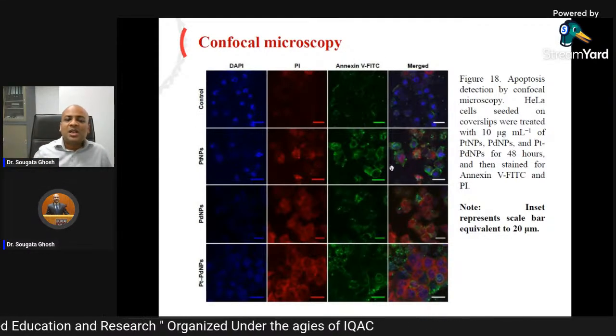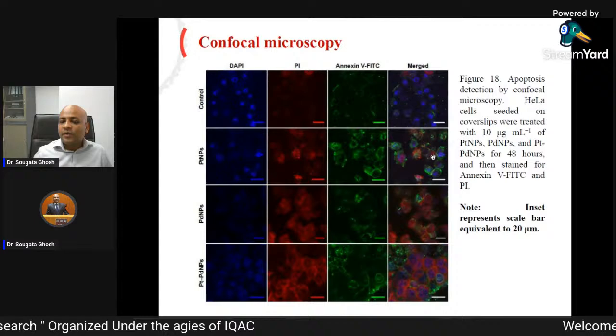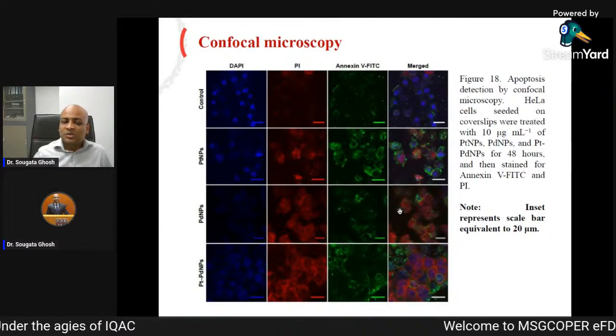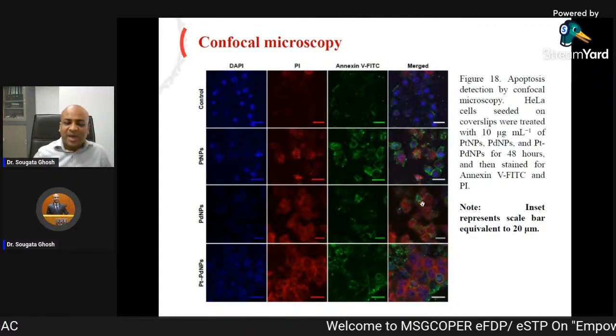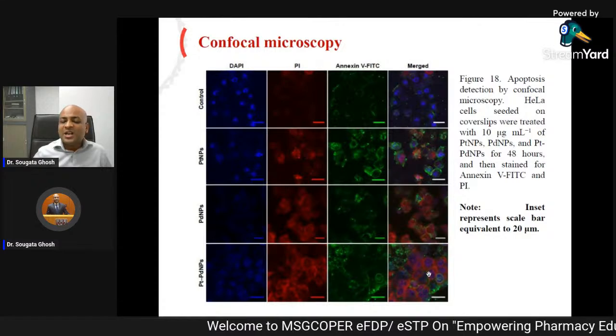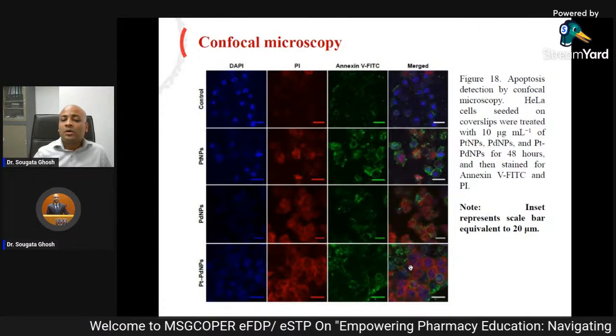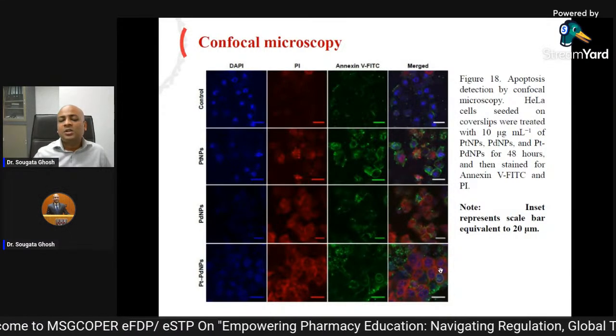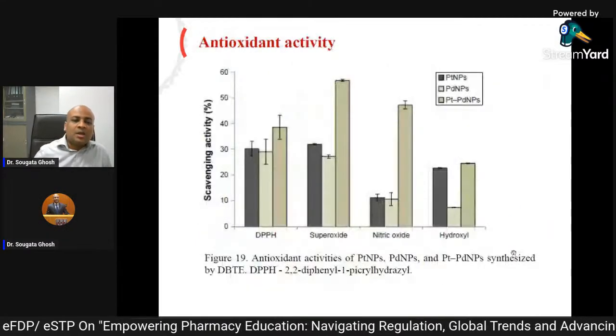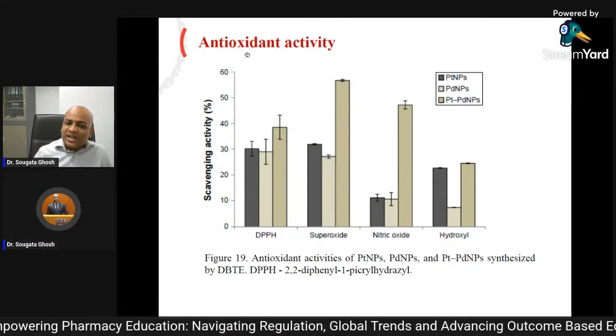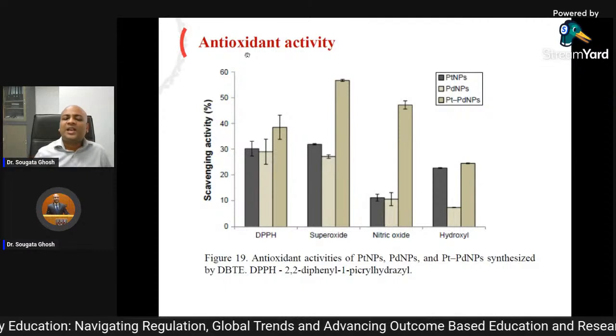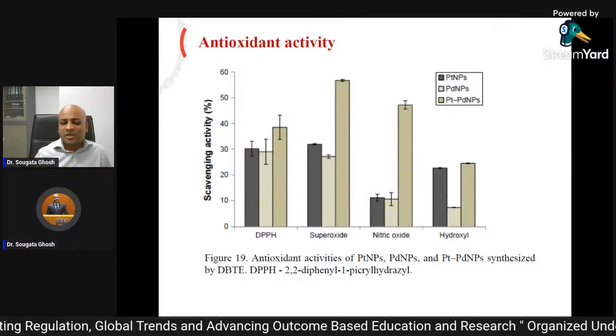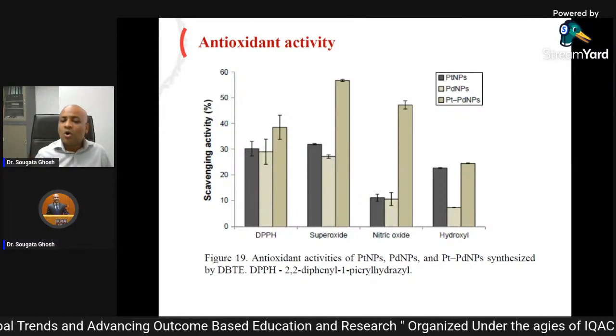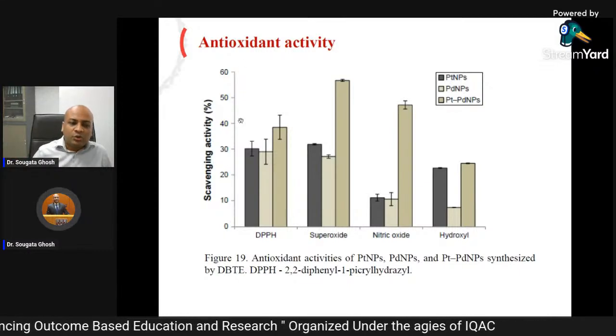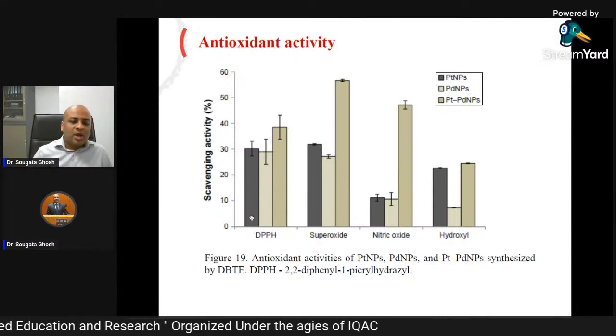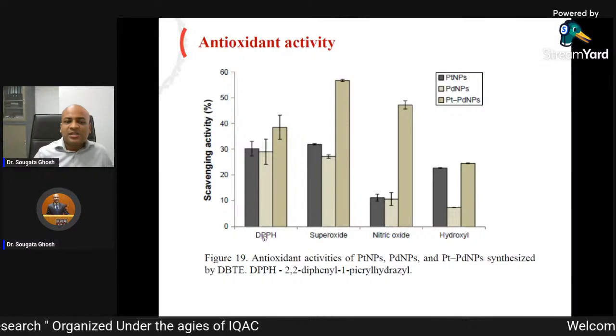So here you can see the dual staining apoptosis over here. Here also you can see apoptosis when we treat with palladium. And when we treat with platinum palladium together, you have a very high amount of apoptosis over here. Now we saw the antioxidant activity also, because generally cancer is caused by free radicals, ROS, reactive oxygen species, oxidative stress. So we wanted to see what is its effect when we are adding these nanoparticles.